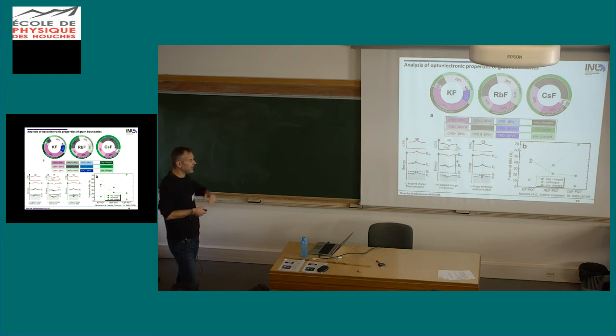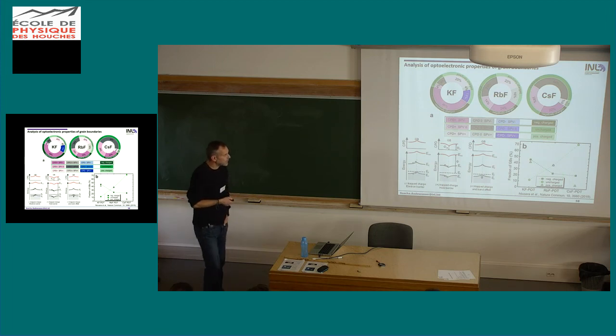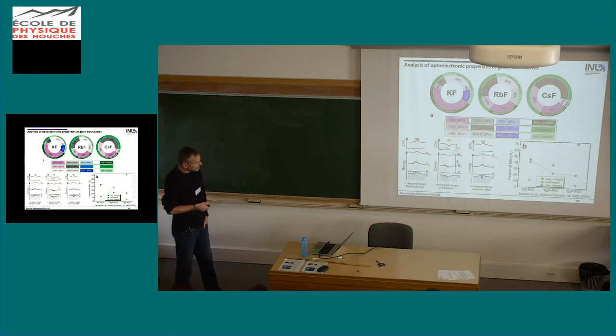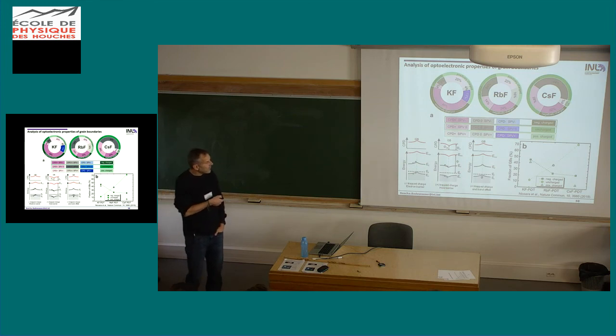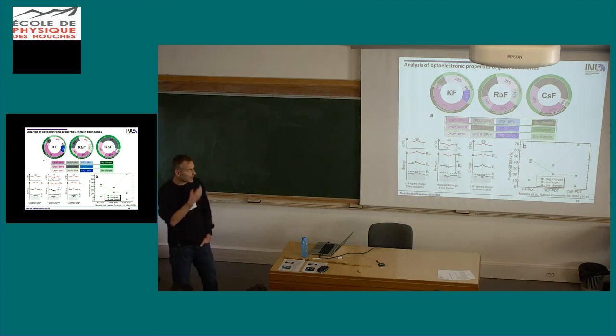It's a whole barrier, but then under illumination, the normal situation would be that we get a reduction in this band bending, and then we can say we have positive charges sitting there. So in the end, we use this analysis to define if we have negative charges, positive charges, or if our grain boundaries are uncharged. And if we look now at this, this is the distribution of values, CPD plus minus.